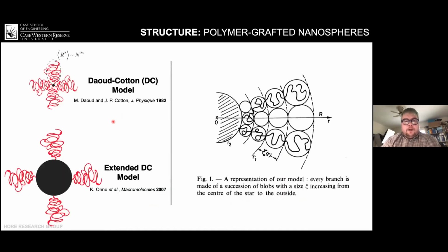And so the starting point for describing the structure is that of the star polymer. And so in 1982, Daoud and Cotton derived a model for how the conformation of an arm of a star polymer should change as a function of distance from the core, as well as a function of the number of arms that are on the particle. Later on, this model was extended to include a large core for the molecule, which is exactly the case that you have when you have a polymer grafted nanoparticle.